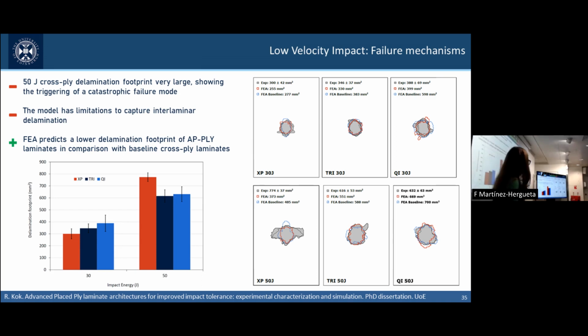What we can really declare here is that there's an advantage on triaxial and quasi-isotropic configurations. They can restrain the extension of the delamination compared to a cross-ply laminate, and also compared to conventional angle-ply laminates. At this level of energy, 50 joules, it is very unlikely to have delaminations that are this small. You will find instead a very widespread delamination, in particular on the rear back faces of a laminate.